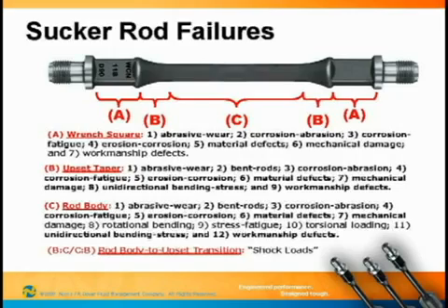Corrosion engineering. We're going to talk a little bit about the materials, and many of y'all are probably aware of this. Corrosion fatigue can be prevented by a number of methods. Increasing the tensile strength of the metal or the alloy improves ordinary fatigue, but is detrimental to corrosion fatigue, particularly in a sour environment. We're more likely to crack once the pitting has already started. And so again, it goes back to that thing a while ago that we looked at. Design for load, treat for corrosion.